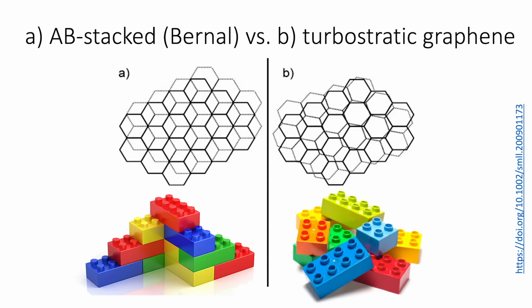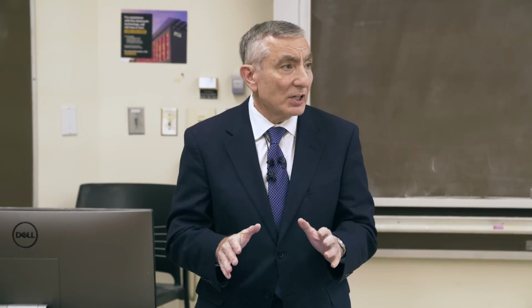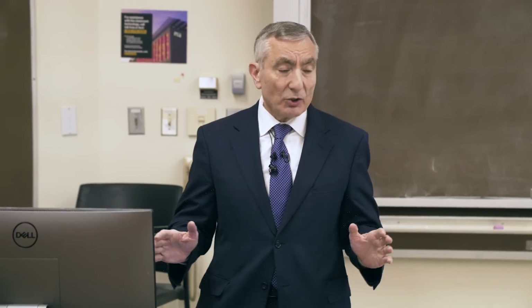And so this is what AB stacked graphite looks like. With AB stacked graphite, you pull it apart, you get one layer just over the next layer, so you get the electron rich over the electron deficient, but it's hard to pull these layers apart. When it's turbostratic, there's no particular adhesion between the layers. And so it's much easier now to blend these into composites when you have turbostratic graphene, and because it forms and cools so quickly, you get turbostratic graphene.